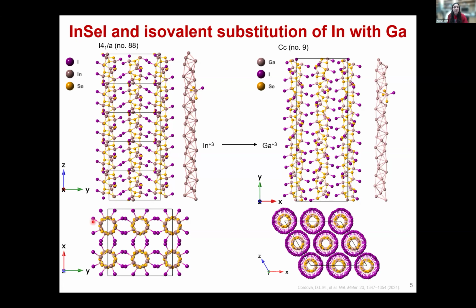However, as I mentioned, because this is a 1D van der Waals material, we can exfoliate this down to a single chain, just using Scotch tape, for example. And recent work in our lab has looked at the substitution of indium with gallium, and we can see a clear change in the helix parameters. The long axis of the unit cell increases almost 5-fold, and the material becomes non-centrosymmetric, crystallizing in the Cc space group. Non-centrosymmetry, while still being achiral, does give rise to various nonlinear phenomena like piezoelectricity and second harmonic generation that are now opened up within this class of materials.